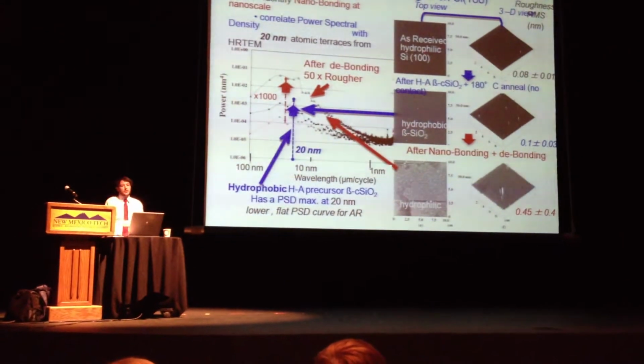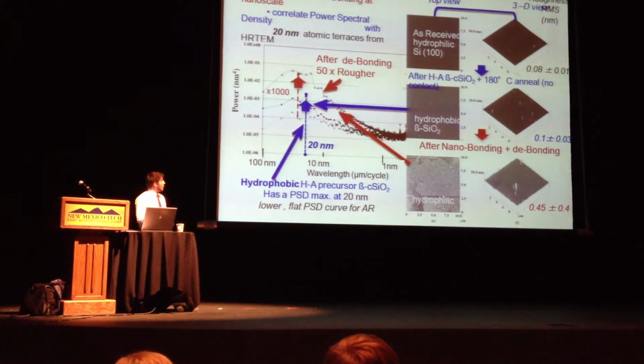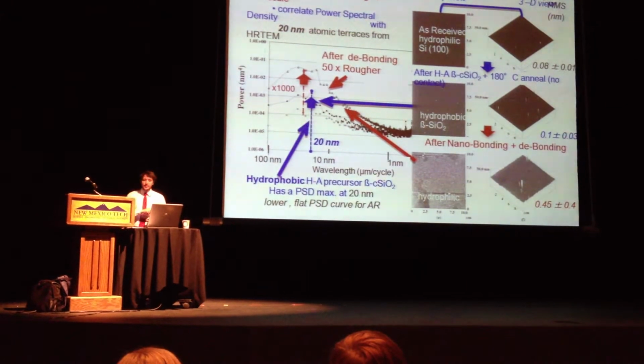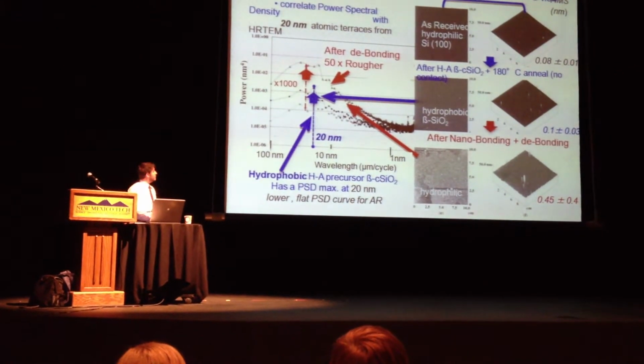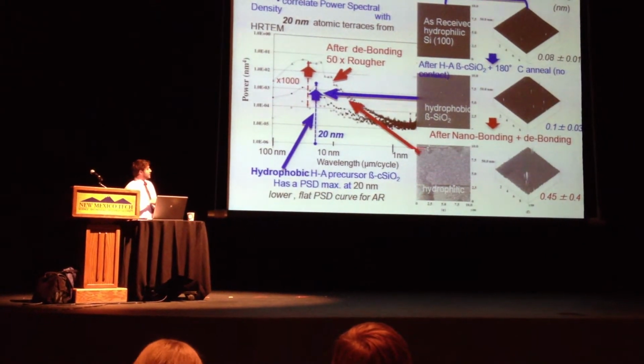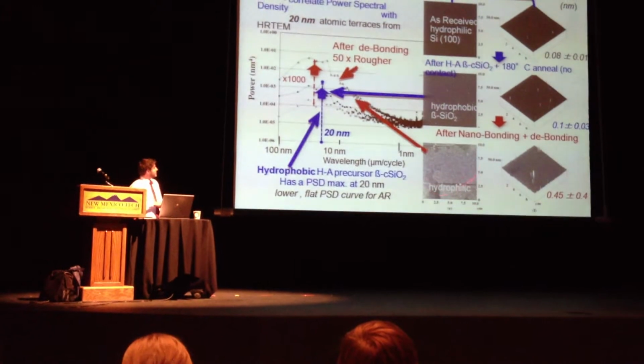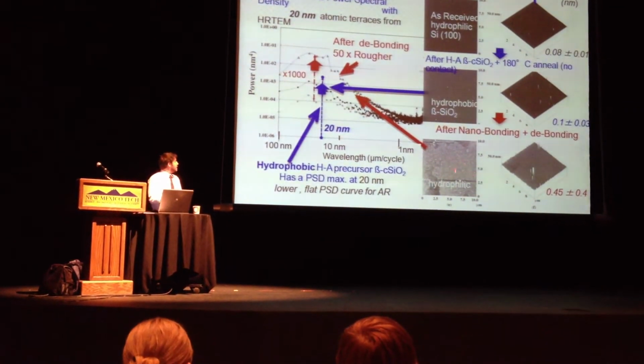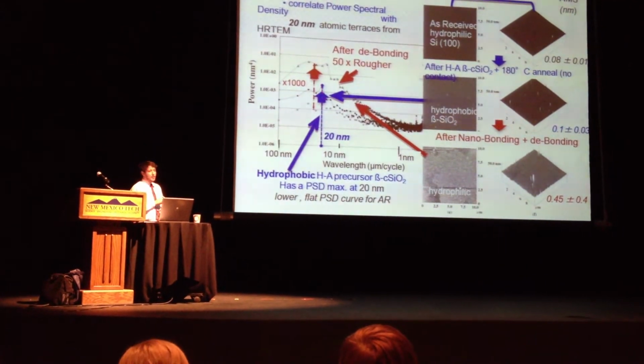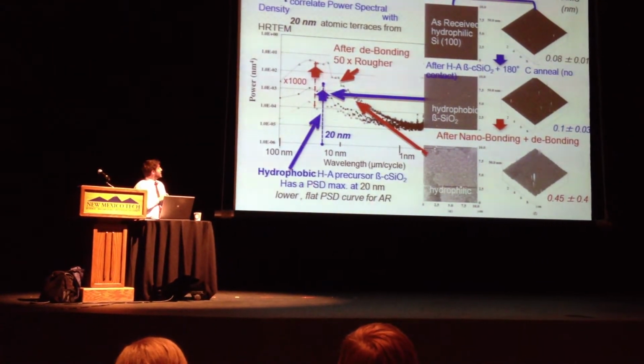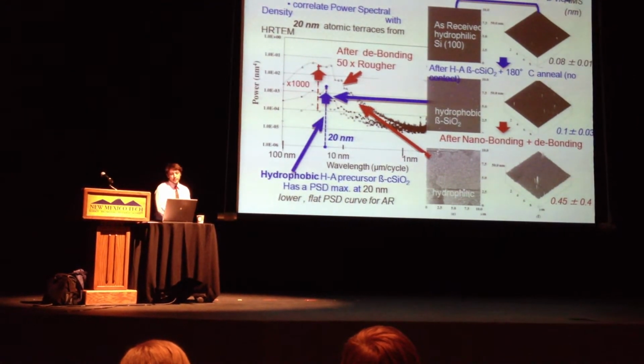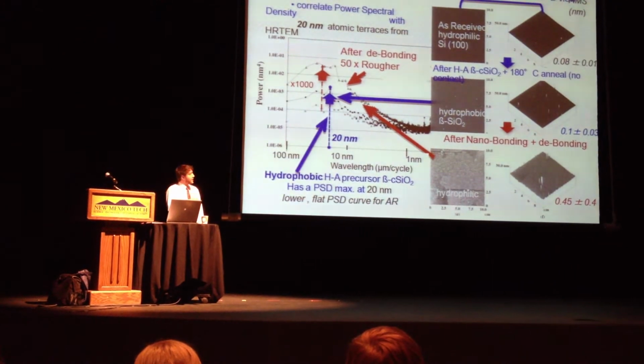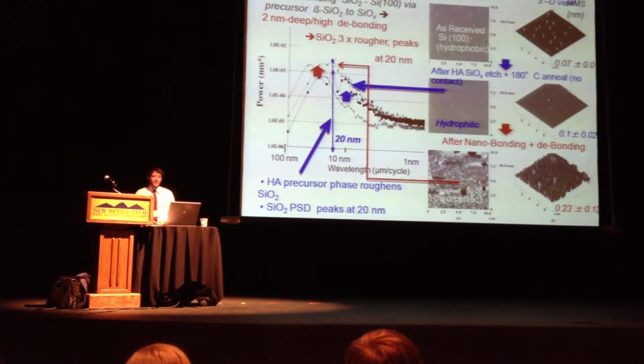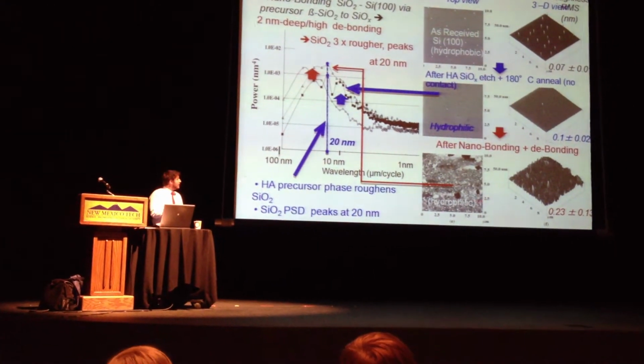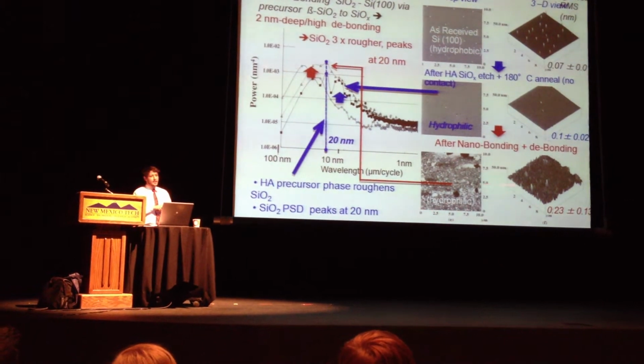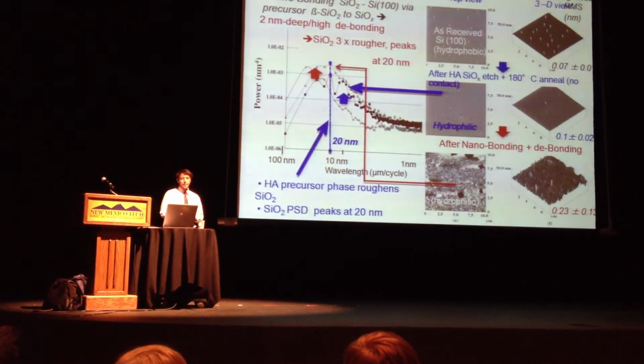And then looking at the atomic force microscopy images of our surfaces to understand our order and what's actually going on, we have 3 different surfaces here, or 2 different surfaces, and then a post-bonding. We see an increase in roughness on the post-bonding, again, evidence of the actual bond. And then we have 20 nanometer peak density or atomic terraces on those surfaces as the highest density. So again, showing the order of the surfaces. And then again, this is on a similar thing. Again, nanobonding and debonding of the silicon dioxide, high roughness, which is going to show the deposit of the oxygen.